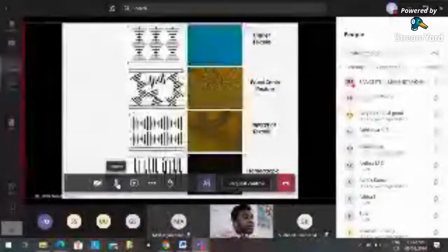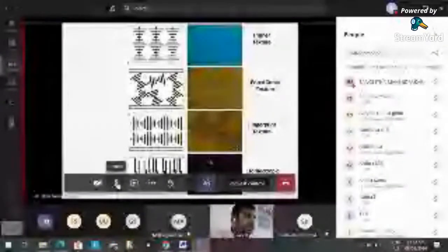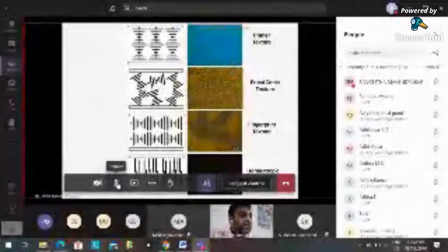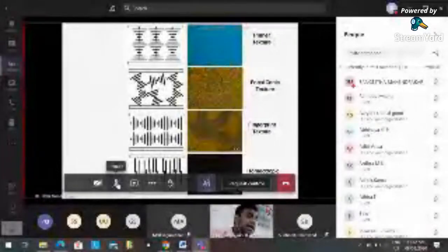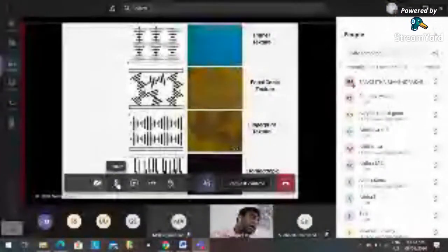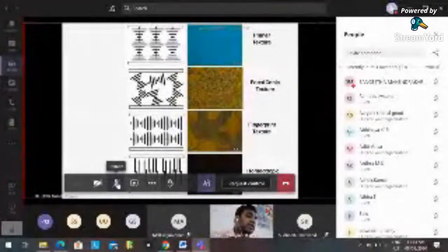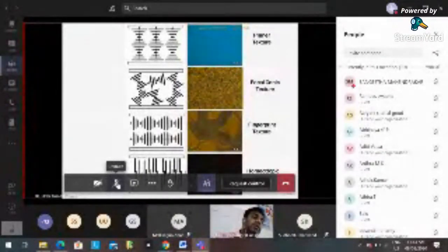So here we have created homeotropic alignment, and according to the homeotropic alignment, we get a dark texture, or we can say a dark state, because these structures are viewed in the polarizing optical microscope, which has one analyzer and one polarizer at a 90-degree angle. That means the light passing through the polarizer is blocked by the analyzer. So we get no color or no response here, and we get a black texture. This confirms that the alignment of the liquid crystals is homeotropic in nature. So this texture is also named the homeotropic texture.